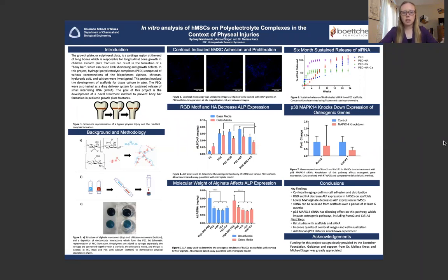This project utilized polyelectrolyte complexes, or PECs, which are formed from oppositely charged polymers — in this case alginate, which is negatively charged, and chitosan, which is positively charged. These polymers interact to cross-link, forming the PECs used as scaffolds for tissue culture and siRNA delivery. These scaffolds contain combinations of alginate and chitosan, as well as hyaluronic acid (HA) and calcium.